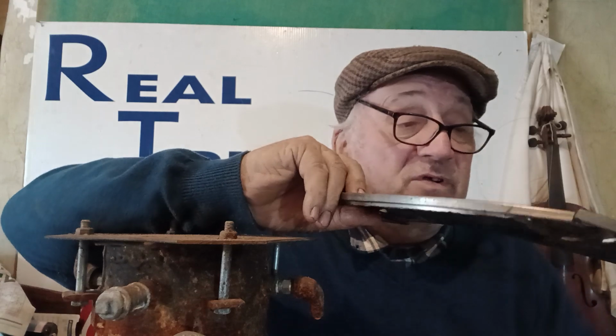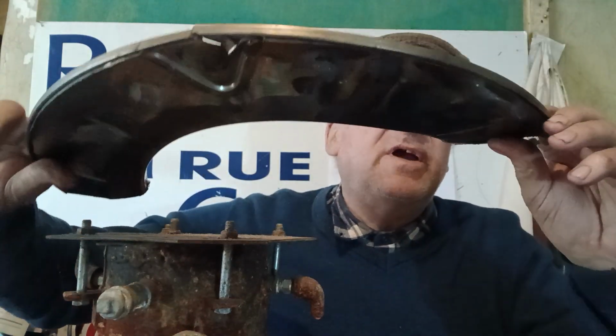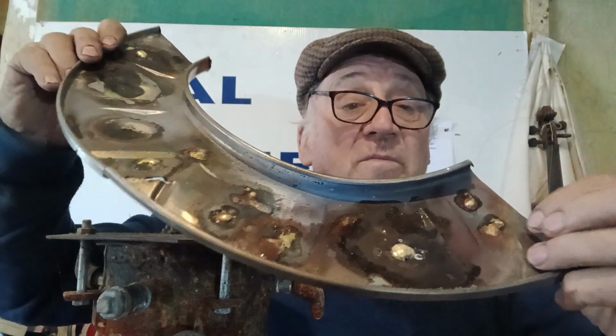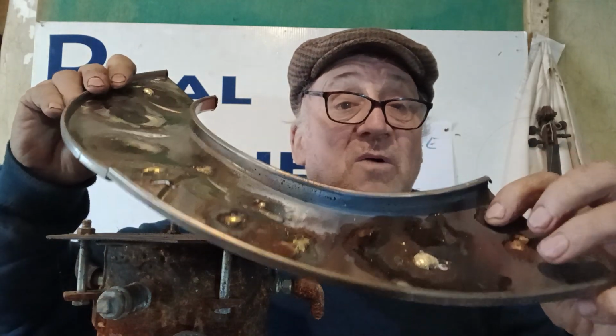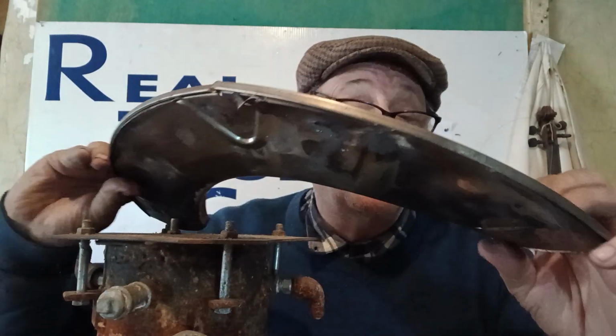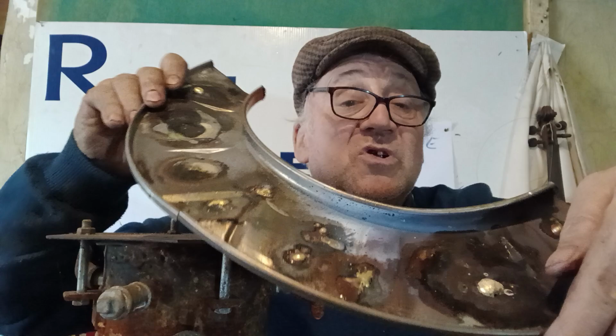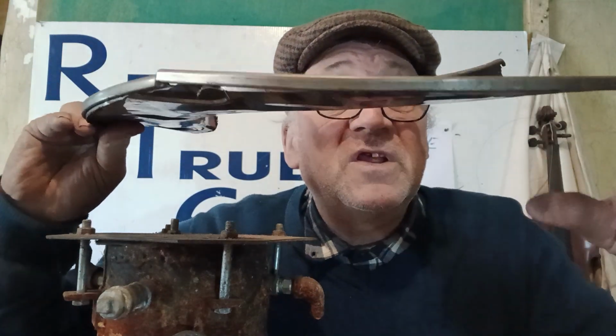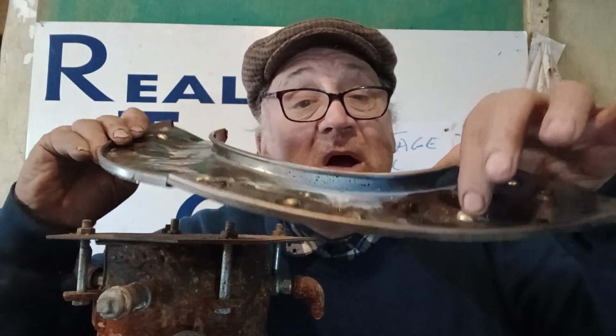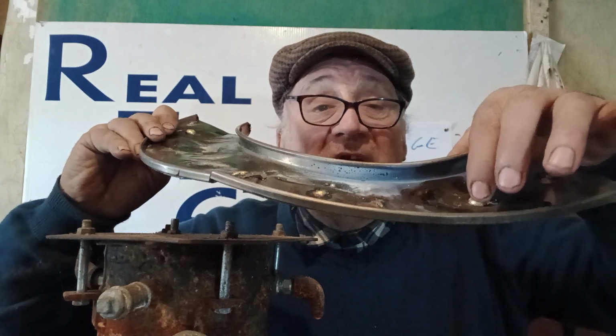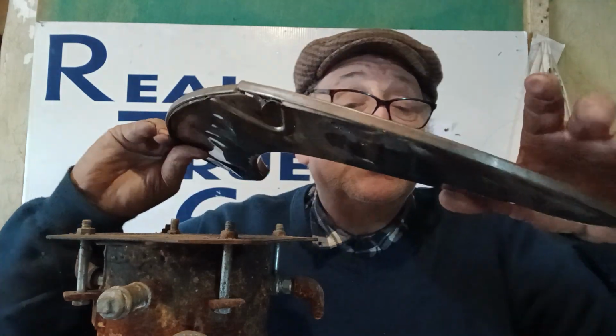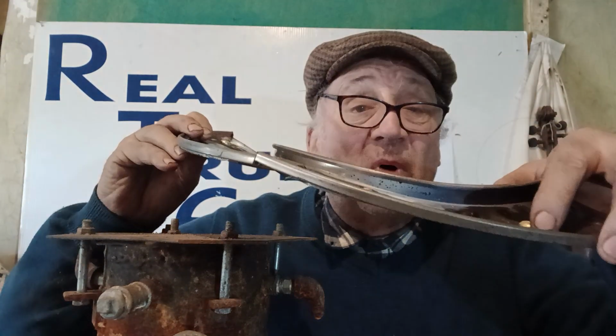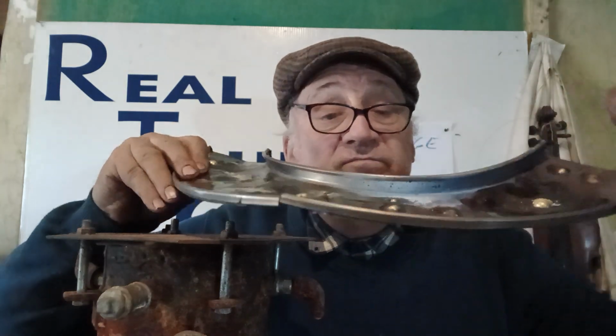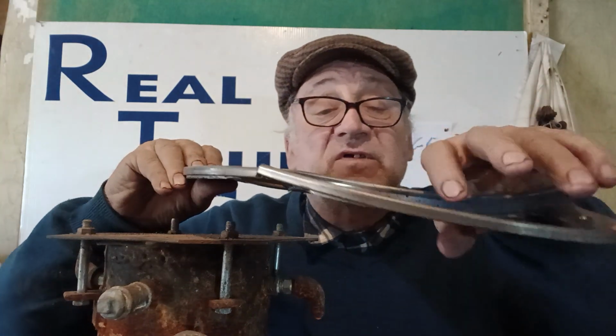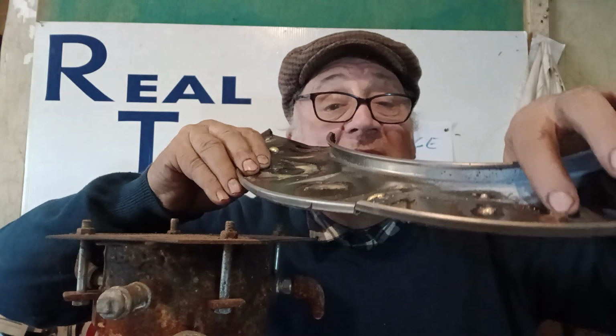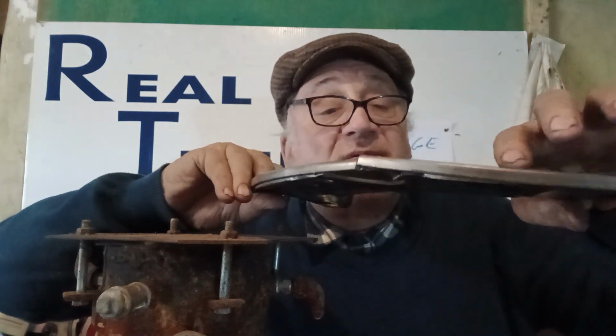So what I've done was I've done a few tests. Here is a piece of raw brass which did work. So it can be done. Here is a piece which didn't. But you see the way it's a lump. Do you see the way it's a mound? It didn't melt right because I couldn't get the heat hot enough to make it melt, and it tended to burn off even the flux. So here is another example, proving that you can weld with brass to this stuff, but it's difficult to do.